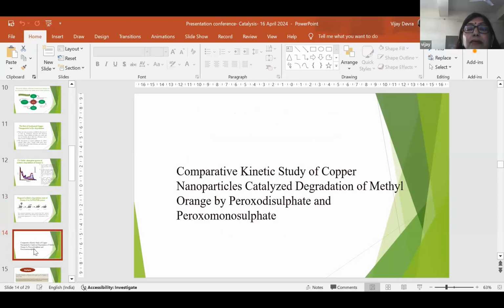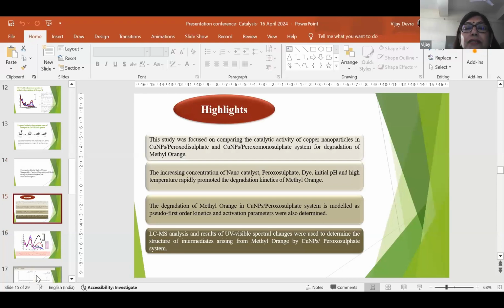Now, I will discuss the comparative kinetic study of the copper nanoparticle catalyzed degradation of methyl orange by peroxomonosulfate and peroxodisulfate. Here I discuss the catalytic activity of copper nanoparticle in both systems, copper nanoparticle peroxomonosulfate and copper nanoparticle peroxodisulfate, for the degradation of methyl orange. I also discuss the various effects of reactant concentration on the degradation rate, and the results indicate pseudo first order kinetics. Activation parameters were also determined, and LCMS results indicate the intermediates arising from the methyl orange by the copper nanoparticle